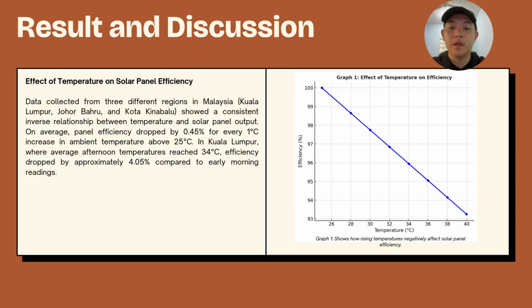On average, panel efficiency dropped by 0.45% for every 1 degree increase in ambient temperature above 25 degrees. In Kuala Lumpur, where average afternoon temperature reached 34 degrees, efficiency dropped by approximately 4.05% compared to early morning reading, as shown in graph 1.